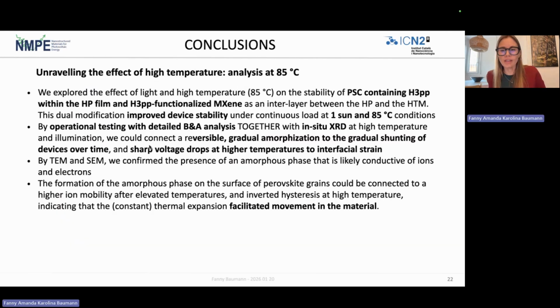So we could also see how the before and after analysis, together with in-situ XRD, really made it possible for us to better connect the chain of events that lead to degradation, and that could lead to improved stability. Even though our modification is not perfect and still needs improvements, we really show a new way of performing stability testing.